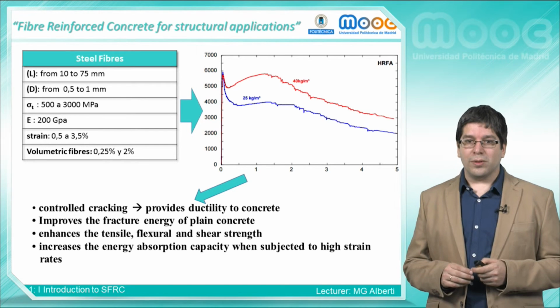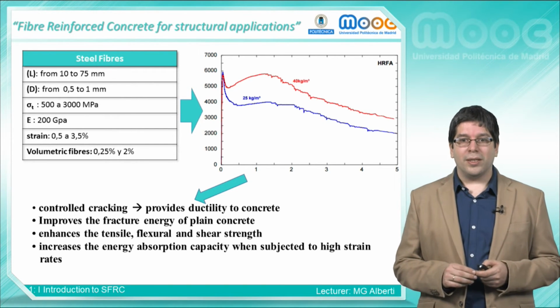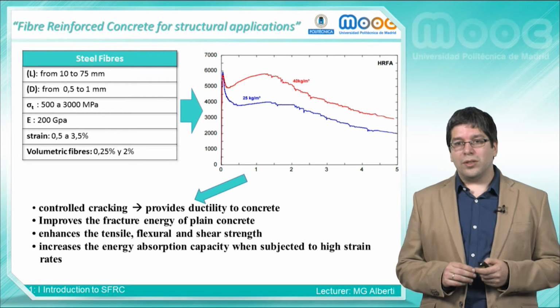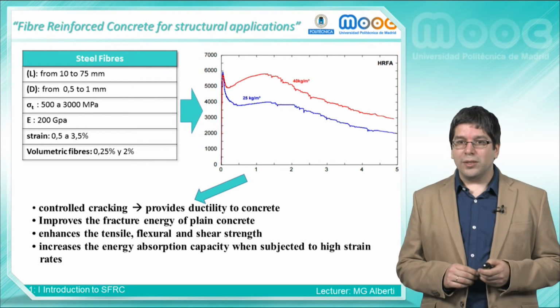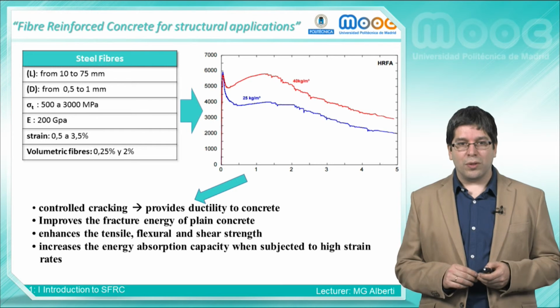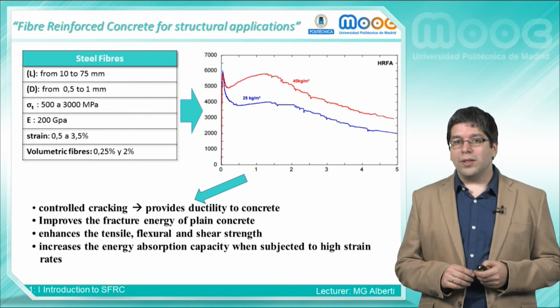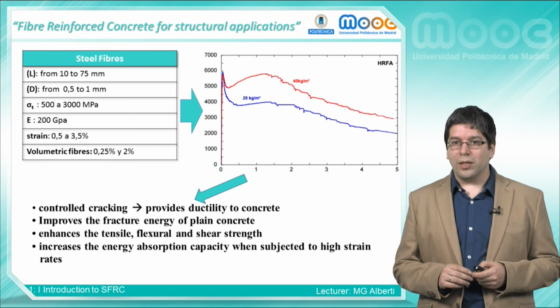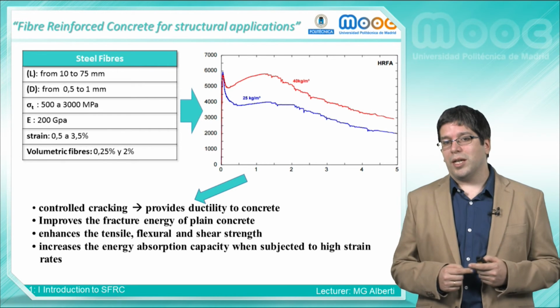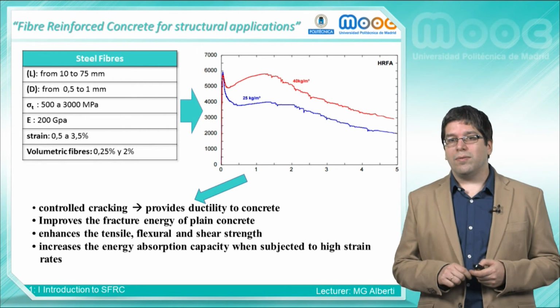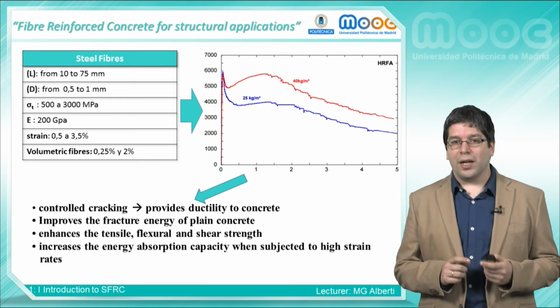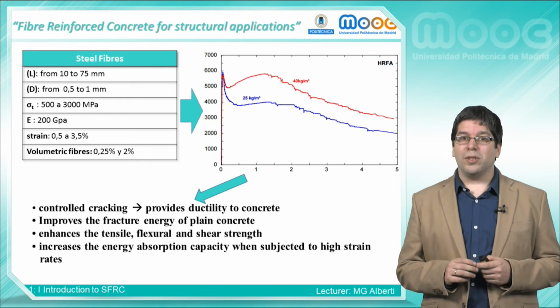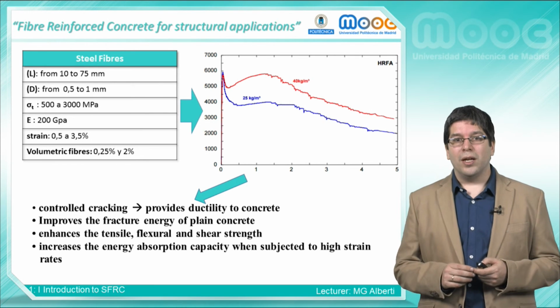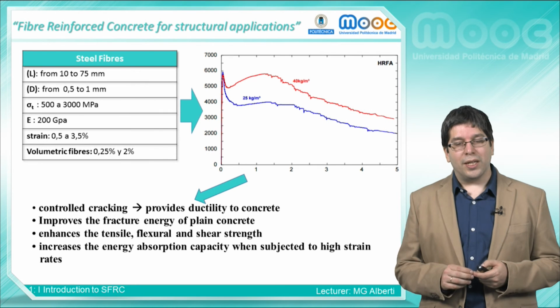This observed behavior shows the following improved characteristics in the material: a controlled cracking that provides ductility to the material and subsequently a safer structural element. In addition, the fracture energy of the material is greatly improved due to the bridging of the fibers in between the faces of the cracked plane. Moreover, the tensile, flexural and shear strengths are heavily enhanced. Finally, the presence of fibers can prevent concrete from spalling when subjected to blast due to the great amount of energy that the material can absorb.